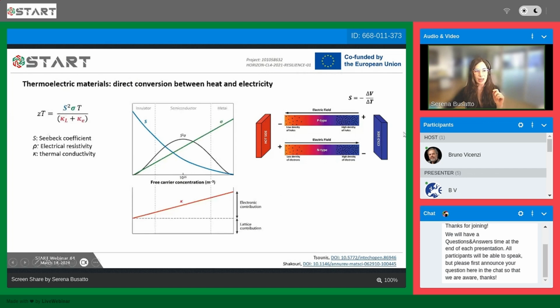Then this is the thermoelectric figure of merit, ZT, and depends on several properties. So the Seebeck coefficient is S, and then we have the electrical conductivity and the thermal conductivity. And as you can see here, unfortunately, the Seebeck coefficient and the electrical conductivity have two different trends. So one is higher for insulators, and the other one is higher for metals. While the thermal conductivity increases with free carrier concentration.